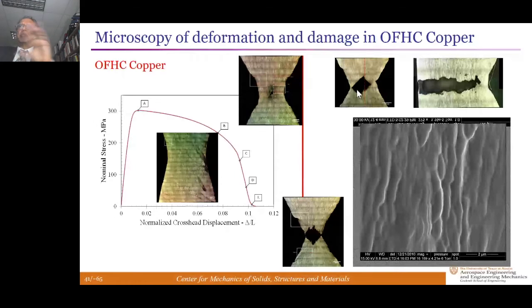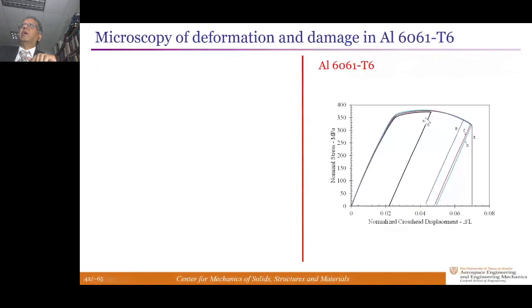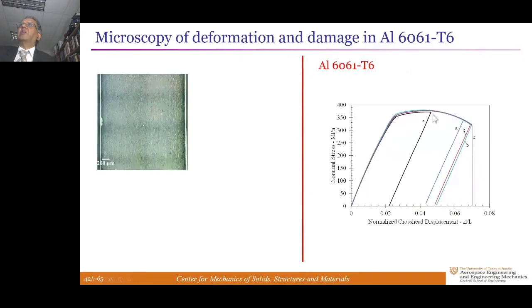The counterpart, the 6000 series aluminum alloy, again, the same thing, unload from A, the width of the specimen is here. You hardly see any evidence of necking at this point. The load has started to drop, localization has started to appear, but no change in the dimensions. At B or C, you see something like this. This is the neck that forms.